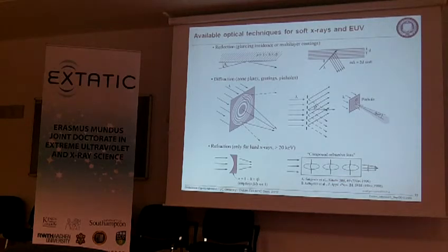So you still get the scattering for the crystal diffraction from the valence electrons, but the absorptive part, where the atoms are, where the K shell electrons are, there's no intensity. And that's why crystals at 25 or 30 kilovolts, if you had near parallel X-rays, for instance in the synchrotrons, they can get like 99% reflection from a crystal. And it's this interference effect which is really playing an important role.